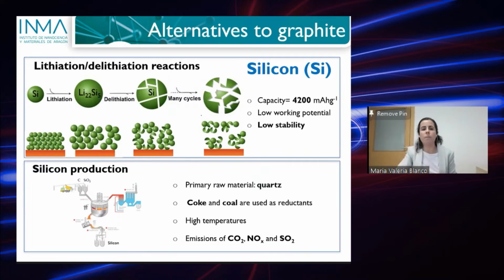So one alternative to graphite is silicon. Silicon has a theoretical storage capacity that is about 10 times higher than graphite, which is really impressive. This is theoretical. It also has a low working potential, which is what we want for the anode material, but it has the problem of low stability.